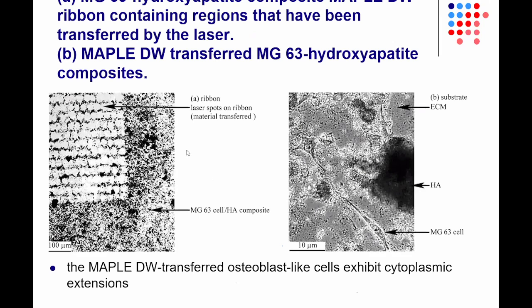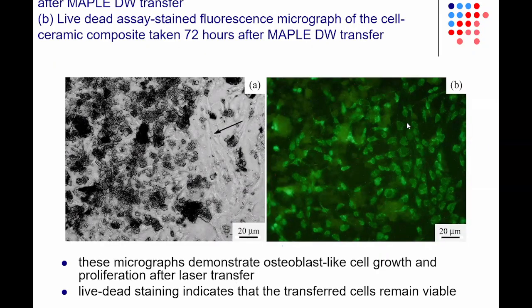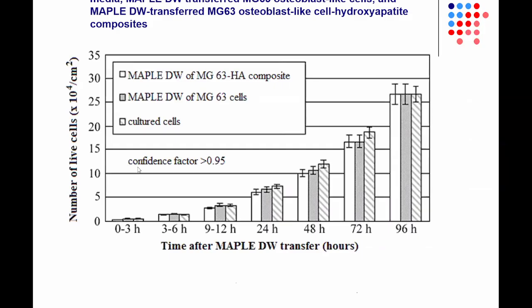Here you can see an example where both osteoblast-like cells, MG63 cells, and hydroxyapatite are spin coated onto a ribbon. Then the laser has interacted with the ribbon to remove certain portions of this ribbon onto another surface. And here you can see the transferred cells, the osteoblast-like cells, the hydroxyapatite, and so forth. This is 72 hours after the transfer. You can see here that you have a high number of living cells and very few dead cells. You look at the viability of the transferred cells. If you perform this at relatively low laser energies, very low laser fluence values, you can get a high number of cells similar to cells grown on polystyrene.